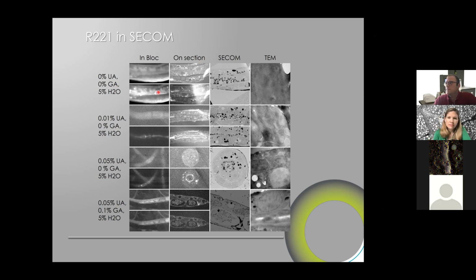And as you can see here, this is reminiscent of what you just saw before. When we have no contrasting agent, no glutaraldehyde, then in TEM, the contrast is close to non-existing. But as soon as you put traces, and I'm talking about 0.01% of UA, so we even decrease the amount of UA, we start to have a high contrast even in SECOM or in TEM. So this is kind of coherent with the semi-conductive behavior of the resin, or what we interpret as being a semiconductor behavior. And then at some point, when we increased the amount of UA, we went up to 0.1% of UA. It's kind of reaching a plateau in terms of contrast and also in the behavior in the SEM. 0.1% is not much better in the SEM than 0.05%.